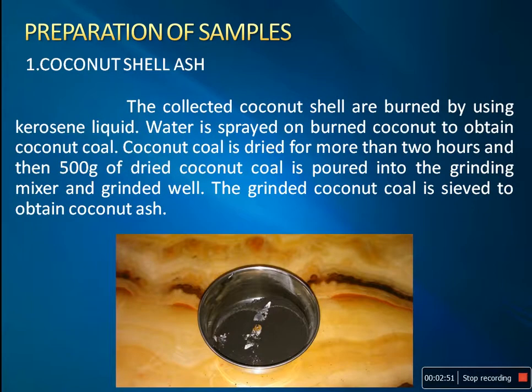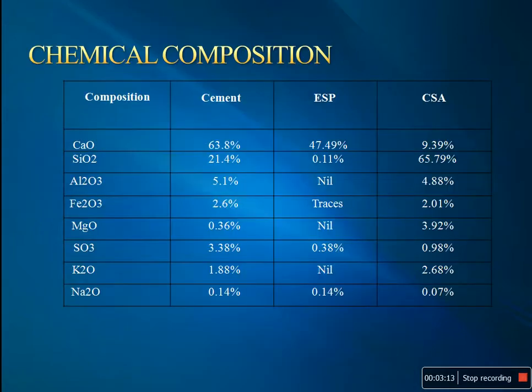The collected coconut shells are burned by using kerosene liquid. Water is sprayed on the burned coconut to obtain coconut coal. The coconut coal is dried for more than 2 hours, and then 500 grams of dried coconut coal is poured into the grinding mixer and ground well. The ground coconut coal is sieved to obtain the coconut ash. The chemical composition of cement, ESP, and CSA.